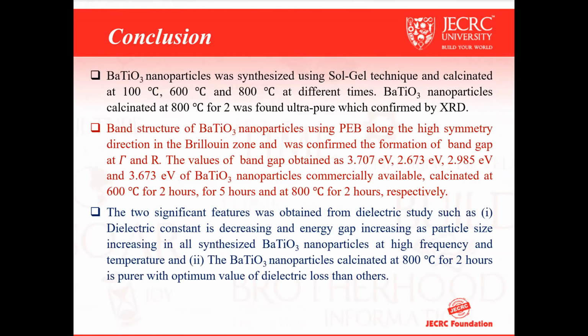On the basis of these optical and dielectric properties, what are the conclusions? The barium titanate nanoparticle has been properly synthesized with the help of the Sol-Gel technique, and we found that the sample calcinated at 800 degrees centigrade for 2 hours is ultra pure. On the basis of band structure, we observe theoretically as well as experimentally that the band gap calculated from the theoretical DFT simulation is nearly the same, and the sample calcinated at 800 degrees centigrade for 2 hours gives a band gap of almost 3.67 electron volt, which we achieved with the help of the calcination temperature effect.